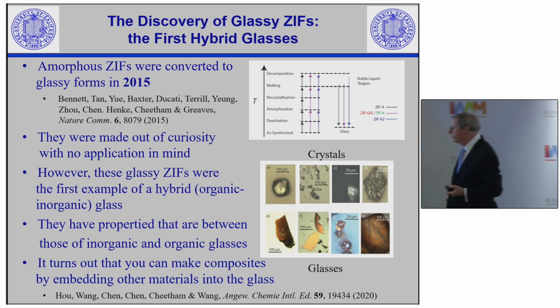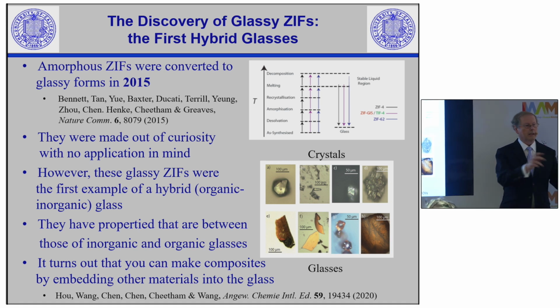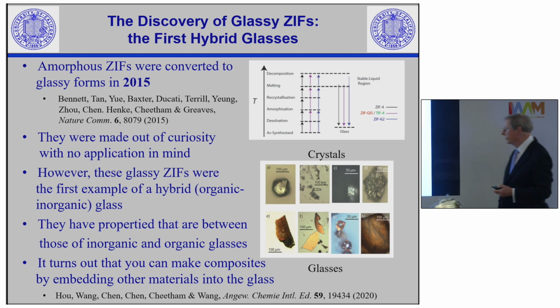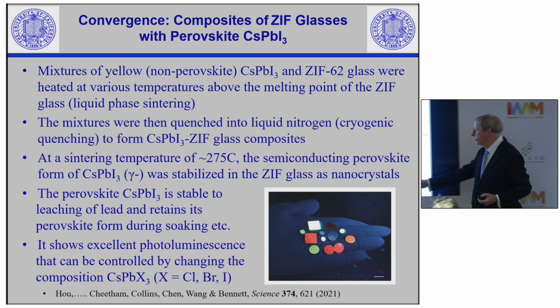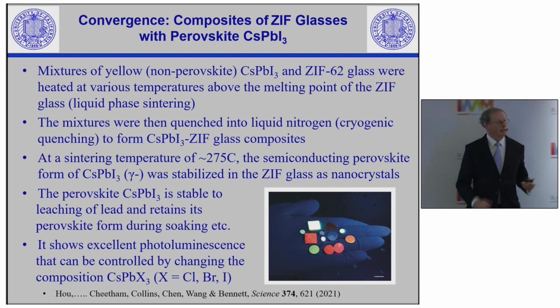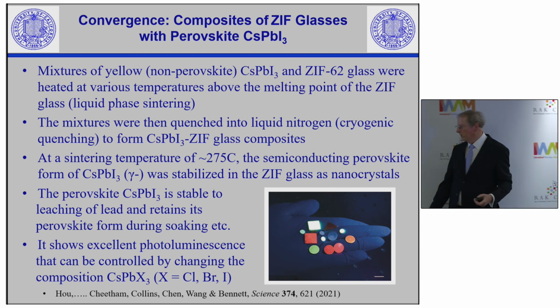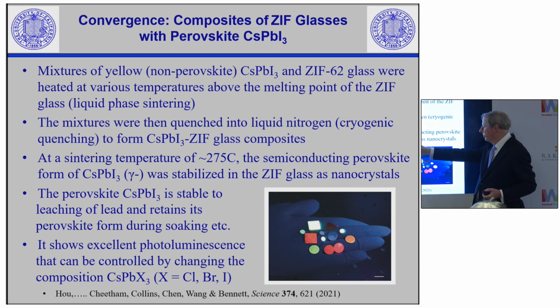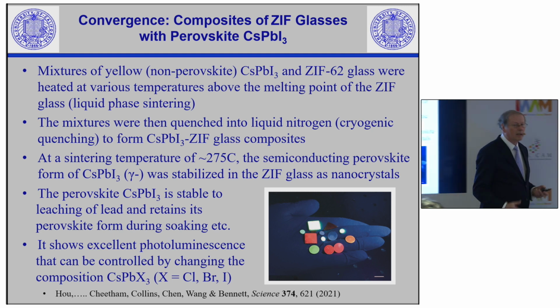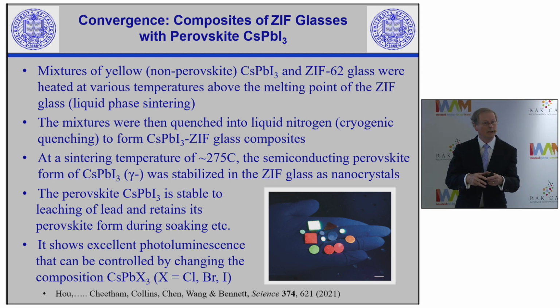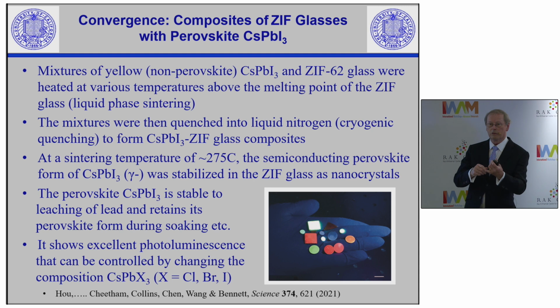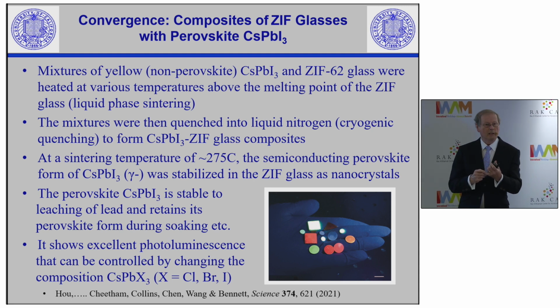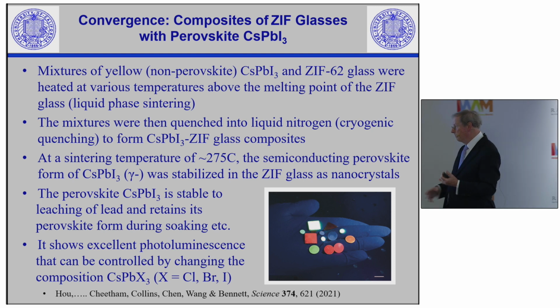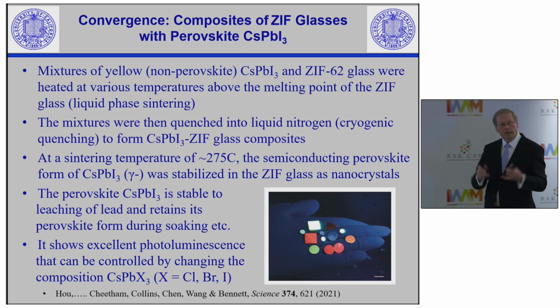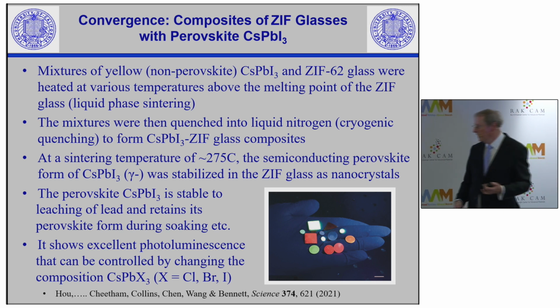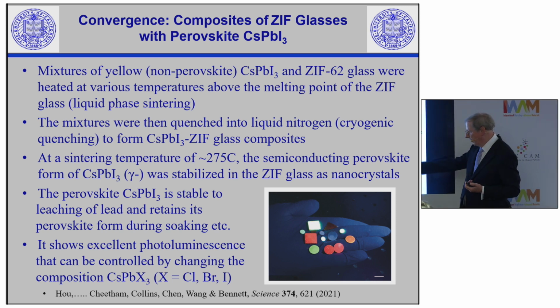And Jingwei Hou, and I hope Jingwei's listening over in Brisbane in Australia, he basically led this tranche of work where he was able to make composites by embedding other materials into the ZIF glasses. And I'm not going to go through this other than to show that what you can do now with the ZIF glass, and this is the convergence, you can take that rather tricky cesium lead iodide and stabilize the semiconducting form in it so that, first of all, it doesn't transform into the regular yellow form at room temperature, so you embed it in the glass. Secondly, it doesn't leach out the lead, which you don't want to happen. And so you can make these beautiful photoluminescent materials.